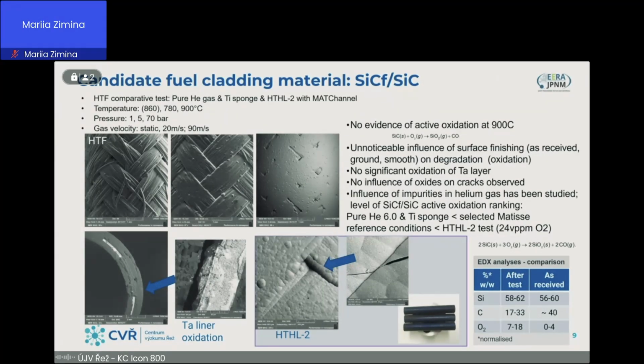conclusion that yes, the silicon carbide suffers when there is no oxygen in the helium, but there will always be some oxygen. So it's about the amount of oxygen present in the gas, because if there is approximately 24 ppm, then we are suffering a somewhat higher oxidation rate, and there is already silica oxide growing on the surface rather fast for such a time.